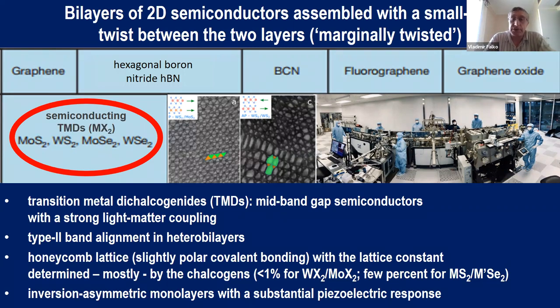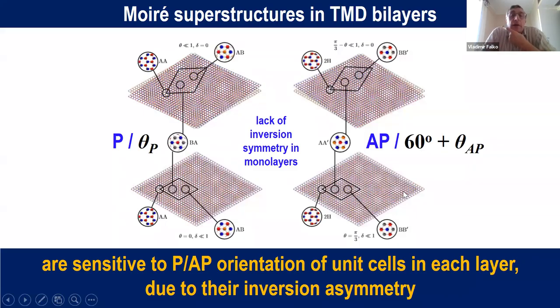So what is the starting point for this discussion? It is that the physics of twisted structures with either the same lattice in both layers or slightly incommensurate lattices with slightly different lattice constants is the physics of moiré superlattices. And in a moiré superlattice, you have a periodic variation of mutual positioning of atoms in the two layers, which has a period dependent on the twist angle.